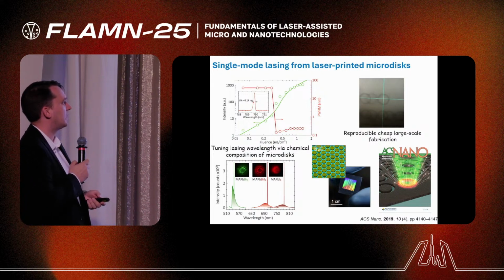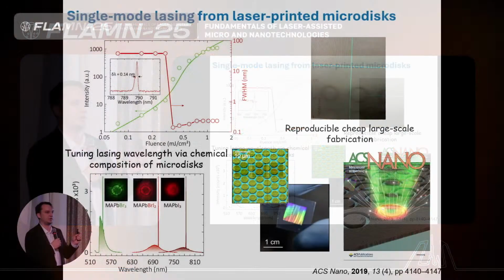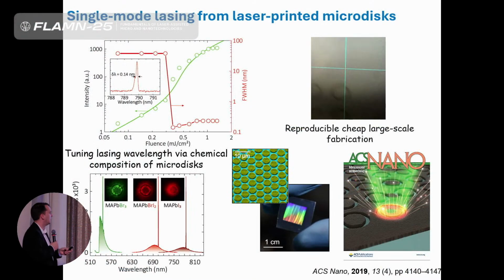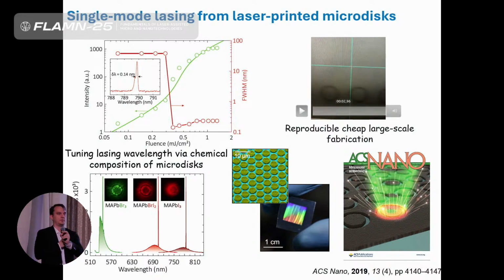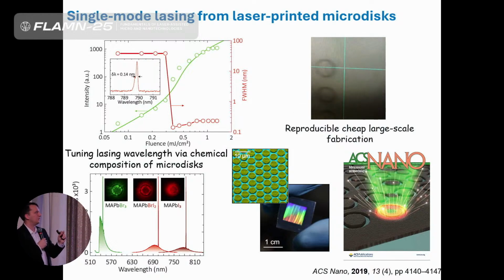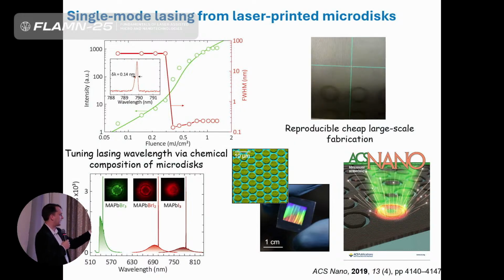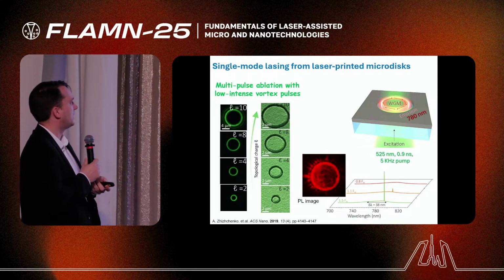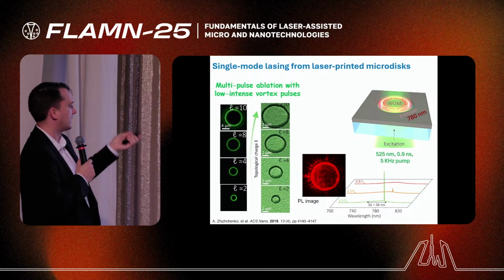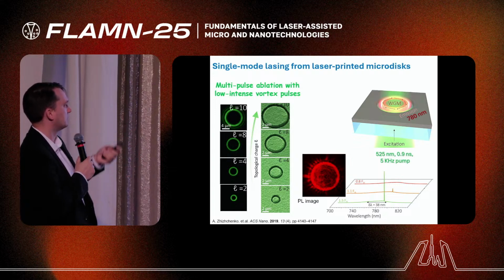So here you see an example of how fast the printing of micro lasers made of perovskite can be. We just deposit a perovskite film by a simple method of wet chemistry deposition, then apply a donut shape femtosecond laser pulse and just print in a few seconds. You can print tens of microdiscs, and in just half an hour we can print a lot of microdiscs on the centimeter scale. So I don't know, millions or billions of microdiscs can be printed just during half an hour. There is some optimization, and the disk diameter can be different, from several micrometers up to any scale.